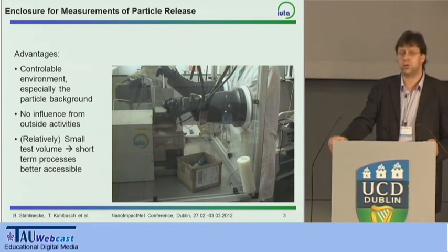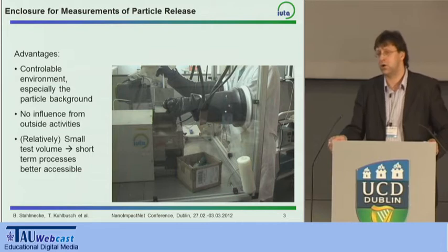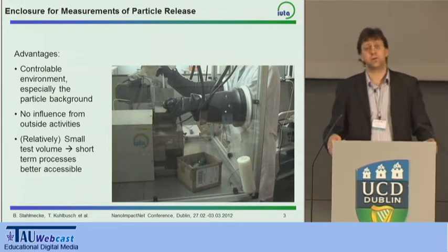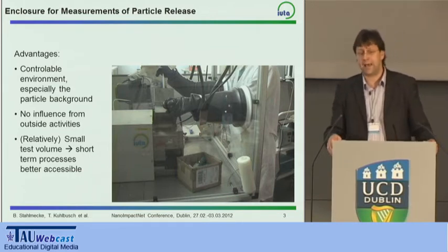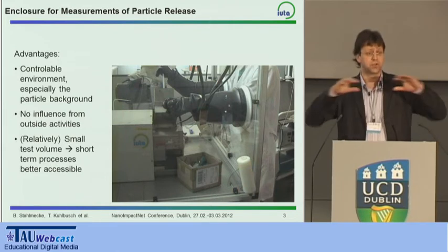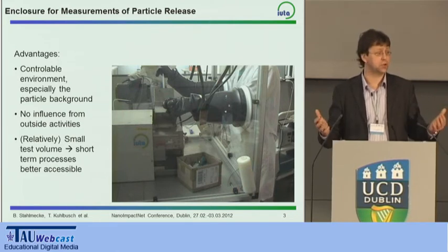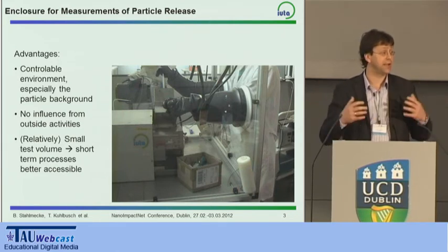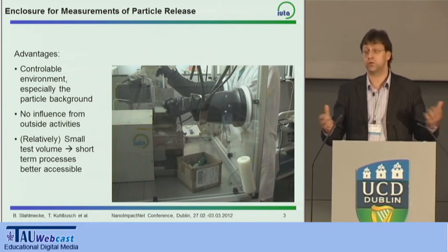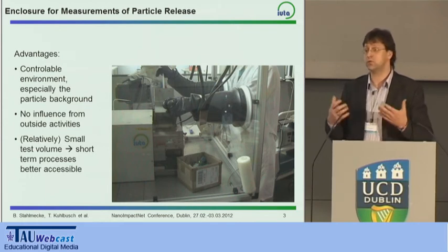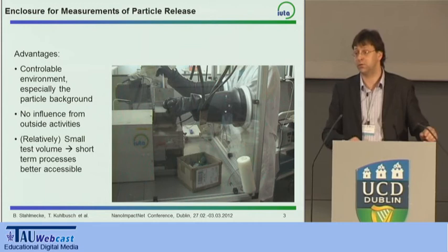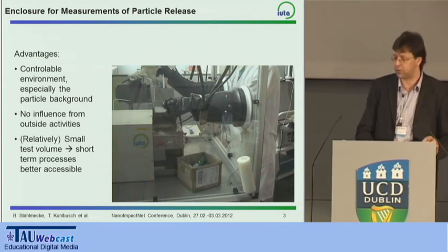The big advantage of enclosures is certainly that we have a controllable environment, which means especially that we know the background particles. We have no real influence from outside activities. And we have a small volume. So if there is an emission, we actually have a relatively high concentration in this small volume. So even small amounts of emission should be detectable within this small enclosure.